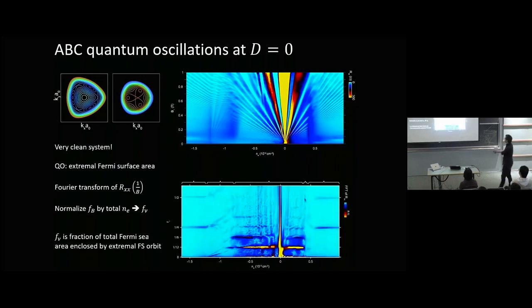So this is what that data looks like when you do all of those things. I'm going to plot it as a function of f_nu, which is this fraction of the total Luttinger volume that a quantum oscillation is probing. And you can see that, so this is again ABC trilayer graphene at 0 electric field, and it's mostly single particle physics. So if we go out at high density, we see that there's a strong peak at f_nu of 1/4. That's just telling you that you have 4 Fermi surfaces that are the same. Which is exactly what you expect in graphene because you have spin degeneracy and valley degeneracy. And so you expect 4 flavors, and you expect at the single particle level that at high density you just have 4 simple, simply connected Fermi seas.